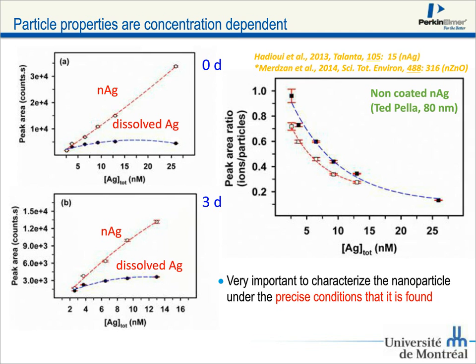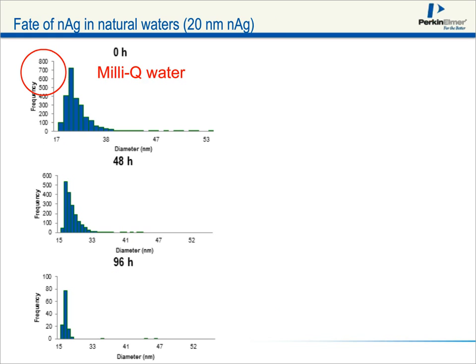Here you see with a single particle another example of that. If we just spike Milli-Q water with 20 nanometer nanosilver, what you see here is with time, as you're going down the figures, you get a displacement of the peak to smaller and smaller particle sizes, and actually the counts go down very substantially as well. So we're interpreting this as being mainly due to dissolution of the nanosilver.